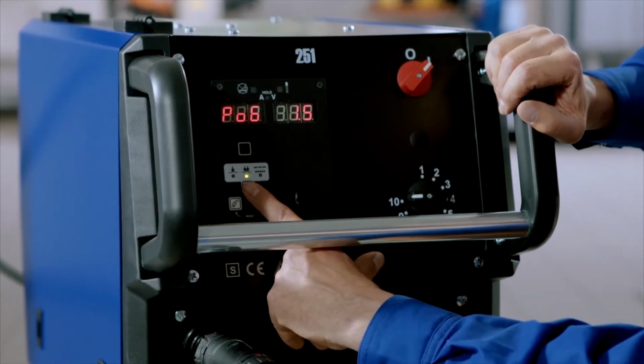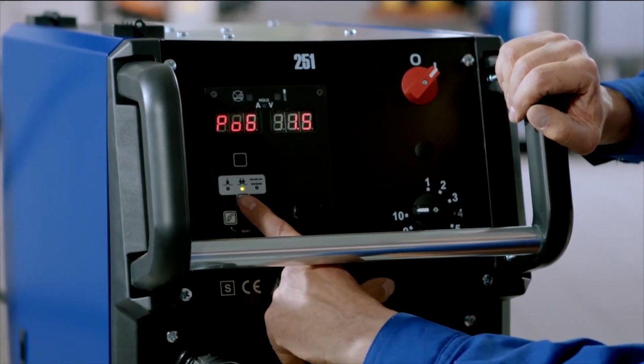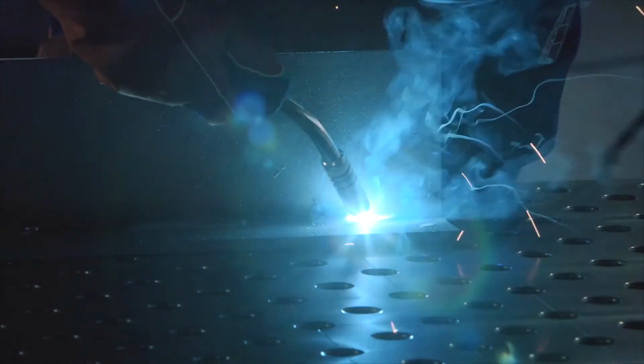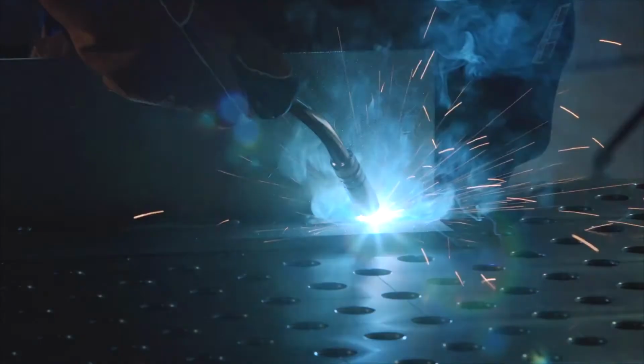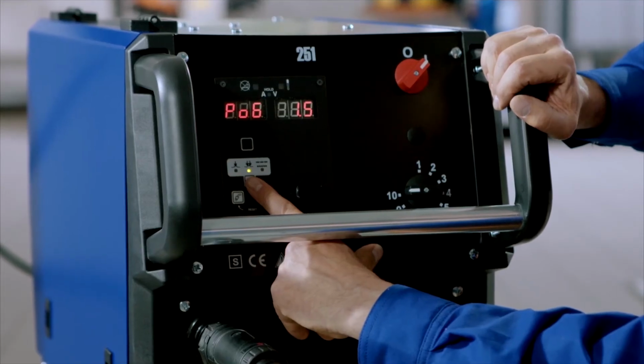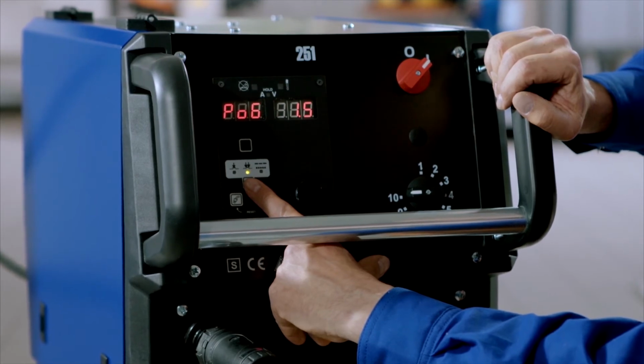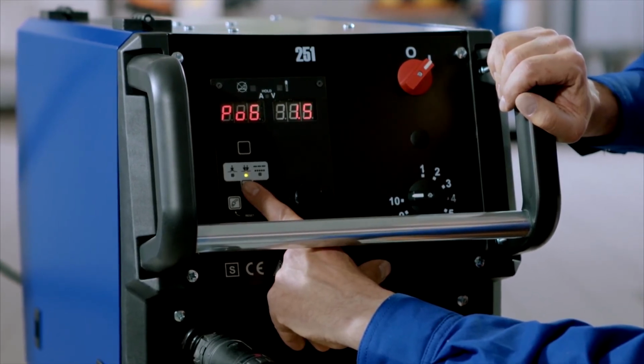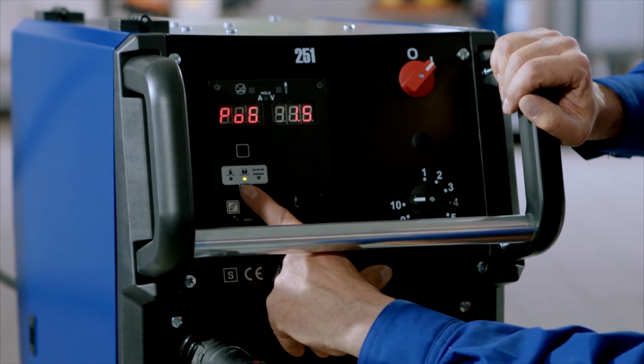Looking now at the gas post-flow time, users who are new to welding should take particular care not to move the torch away too quickly after welding, as the weld metal will still be glowing. To protect the hot metal from the ambient atmosphere and achieve a perfect welding result, set the gas post-flow time to between 1 and 2 seconds.